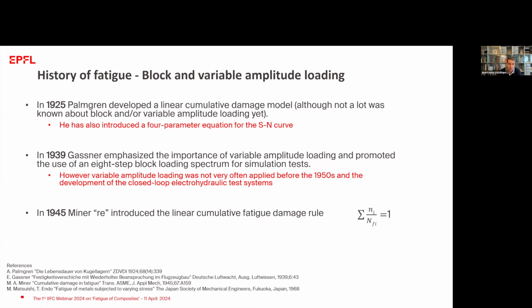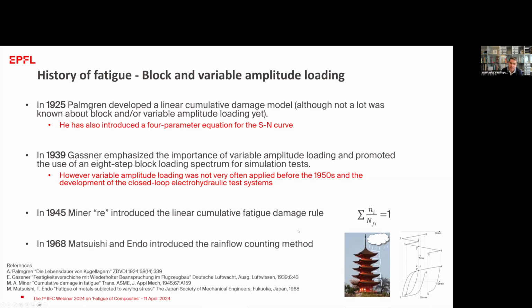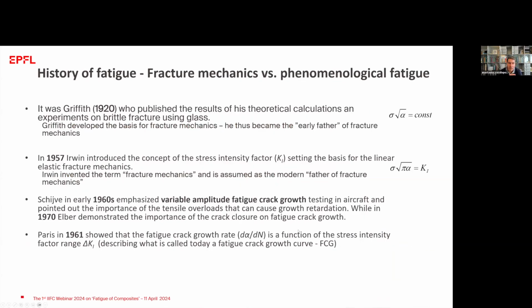a variable amplitude loading. And it was at this period, more or less, between 1925 and 1945, where we had Palmgren and Miner introducing this cumulative fatigue damage rule that we still use today, although we know that for composites it's not very successful in predicting the lifetime. What I was saying until now was based on phenomenological investigation. So we do a test, we measure the number of cycles to failure, and this is observation, it's phenomenological.